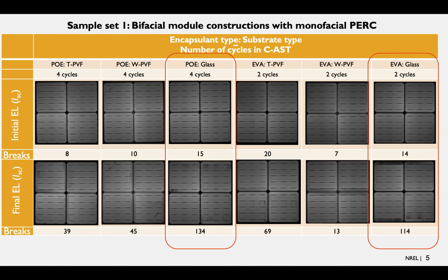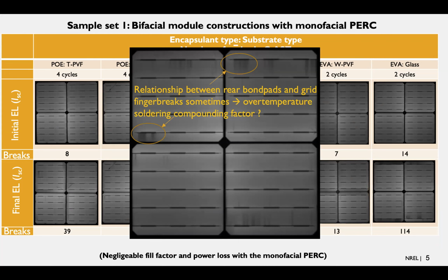Okay. So Dave asked a follow-up question on this slide, which is with the glass mini modules and grid finger breaks, did you see this on both sides or just on the back surface? We didn't do cross-sectional metallography on these samples for a deep dive, but what we're looking at here in this particular electroluminescence image is through the front of the module, although we also looked at the back. But what we're looking at here is rear bond pads. We know they're rear bond pads because when we look at the front of the cell, they try to minimize shadowing, they try to minimize silver, and you don't see any large pads like this on the front of the cell. So we know that these large dark areas correspond to bond pads on the rear of the cell.